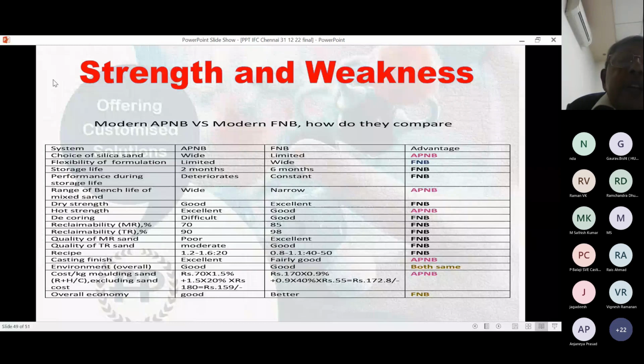Performance during storage life in Alphaset deteriorates, particularly in summer. If you use it after 7 days of manufacture and after 17 days of manufacture, you will find a difference in reactivity. Then range of bench life of mixed sand in Alphaset is wide. Furan is narrower than Alphaset. Then dry strength is good for Alphaset, but excellent for Furan. Hot strength is excellent for Alphaset, good for Furan. Decoring is difficult for Alphaset, good for Furan.